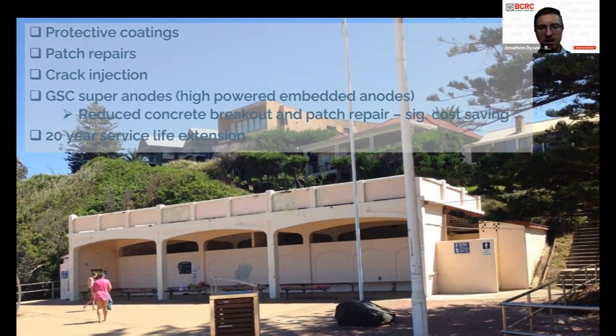And then in this case, we specified a mixture of protective coatings, patch repairs, some crack injections, and some super anodes, GSC super anodes, which are high powered embedded anodes in the concrete to reduce the amount of concrete patch breakout and concrete repair that was required if just those lower powered cathodic prevention anodes had been used. And we were able to achieve a 20-year service life extension for that one. And I'm pretty sure that it was an ACRA member contractor that might have done the repair on that one for us. So that was good.